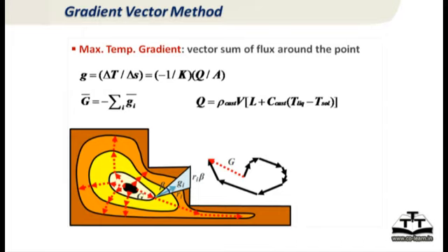What was discovered, and the big landmark discovery here, was that the net gradient or the resultant gradient in a particular direction is nothing but the vector sum of individual gradients around a particular point. If you see that small blue triangle, you see the small gi. Gi is a gradient in a particular direction, and the gi equation is already given to you. But if you take a vector sum of the individual gi's around the point, that is what you see in the black lines. The vector sum is finally from the starting point to the ending point. That is the red line.